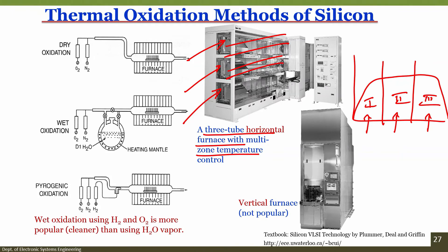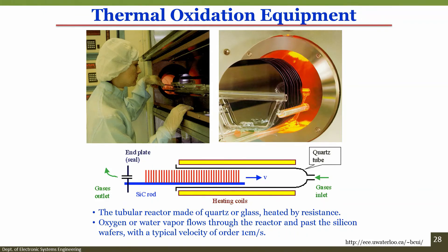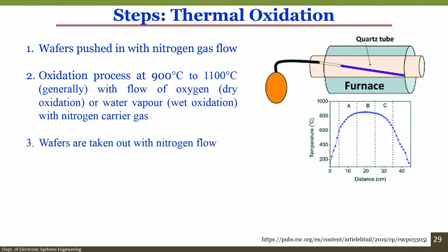Each of the three tubes also has three independently controlled zones. There is also a vertical tube furnace, though the horizontal tube furnace is more popular. The quartz tube is used, and a SiC rod pushes the plate inside the tubular reactor, which is glass or quartz heated by resistance. The process steps are: wafers pushed in under nitrogen gas, oxidation between 900–1100°C with either oxygen flow (dry) or water vapor (wet), and then wafers taken out again under nitrogen.